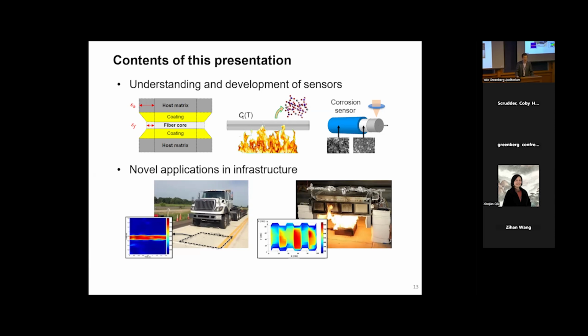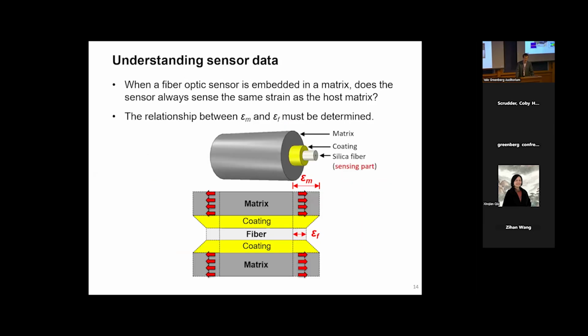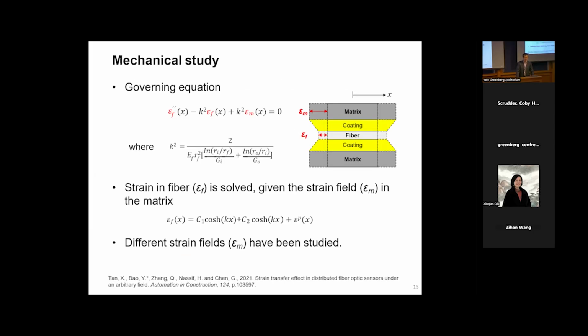So I will talk about our basic understandings of the sensors and some representative collaboration applications. First, we want to clarify that when we have a packaged sensor, this sensor will not provide the accurate measurement directly, because there's a layer of coating. This coating will have shear deformation, so the strain sensed by the optical fiber is different from the host matrix because of this shear effect. So we have to determine their relationship.